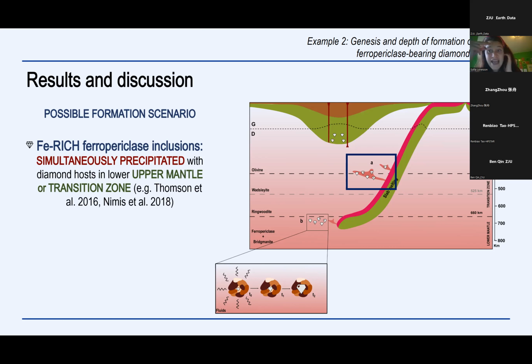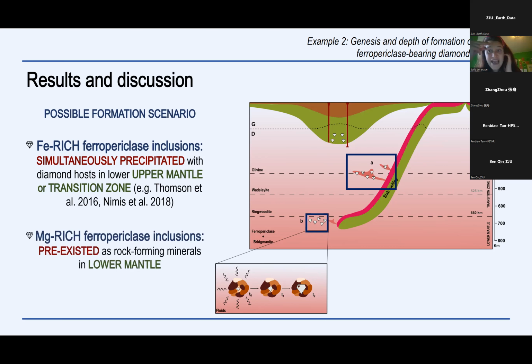And on the other hand, conversely, the magnesium-rich ferropericlase inclusions are pre-existing, rock-forming minerals, dissolved and trapped by the diamonds during their formation in the lower mantle. And this is because the chemistry of these ferropericlase inclusions is similar to the chemistry of ferropericlase predicted by the experiments.